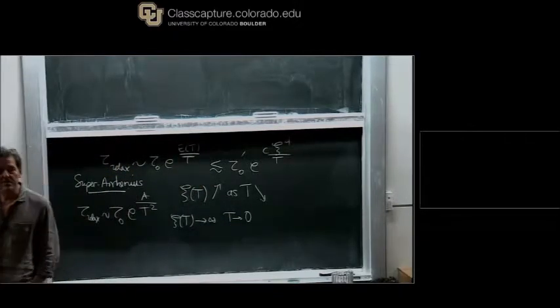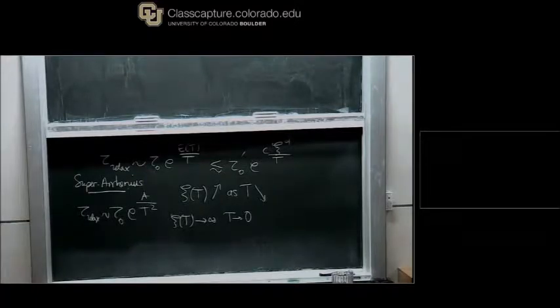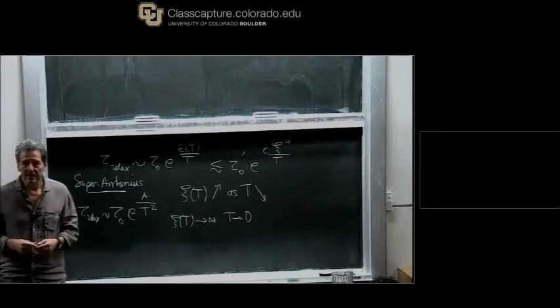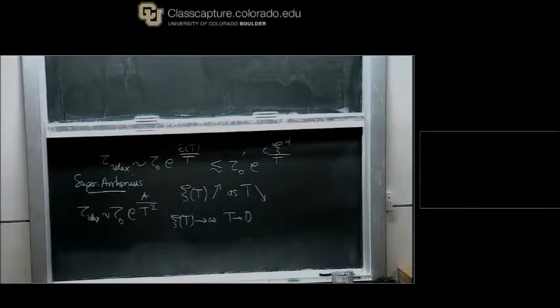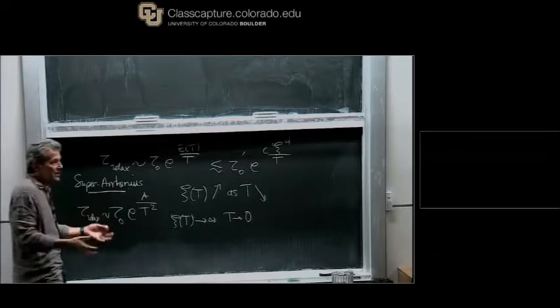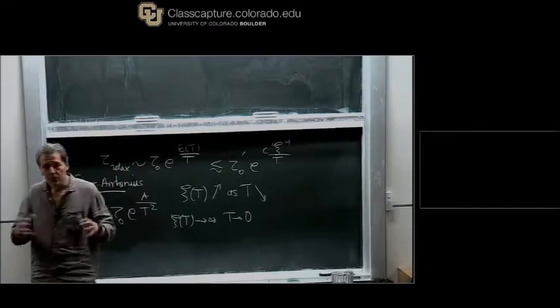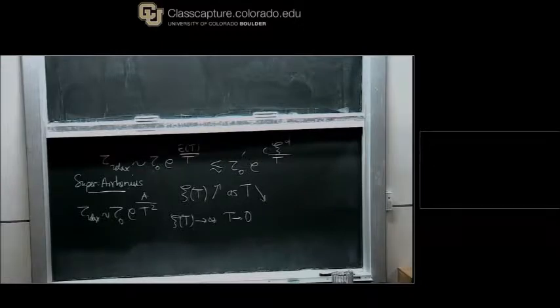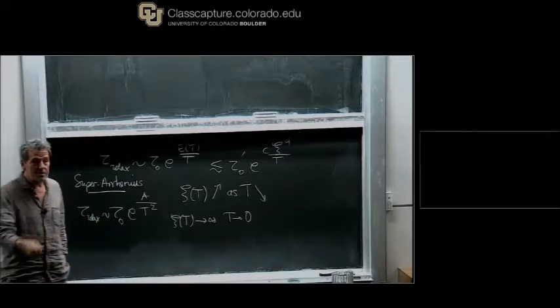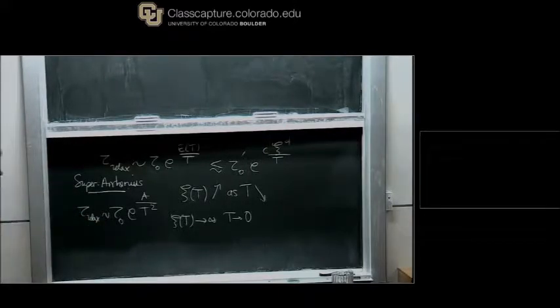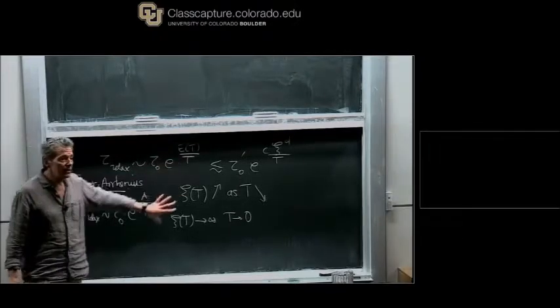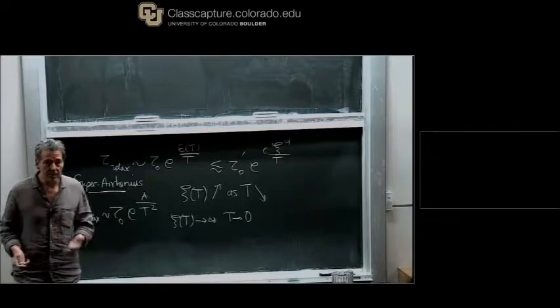Okay, so it's telling you something, that indeed what I said before, again with kind of hand-waving arguments, that if you have super Arrhenius behavior, this is indicative of collective behavior. Degrees of freedom, up to a length, of course, have to be together, conspire, have collective behavior to produce the barrier that grows and becomes larger than just the microscopic barriers or the bare energies. Well, this is basically telling you this in a more rigorous way.